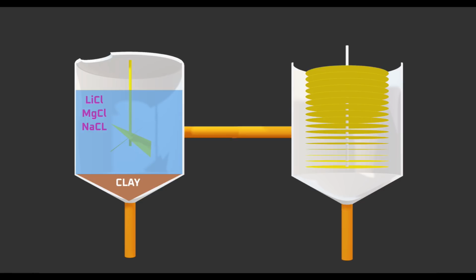The second material we're left with after clarification is an aqueous solution that contains a mixture of dissolved metal salts. These salts could include lithium chloride, magnesium chloride, and of course the sodium chloride that was added to extract the lithium from the clay. But the salt we're most interested in and targeting for extraction is lithium chloride. In other words, what we have after the clay has been precipitated out is a dilute lithium brine. This brine would be drained into another tank to undergo extraction.